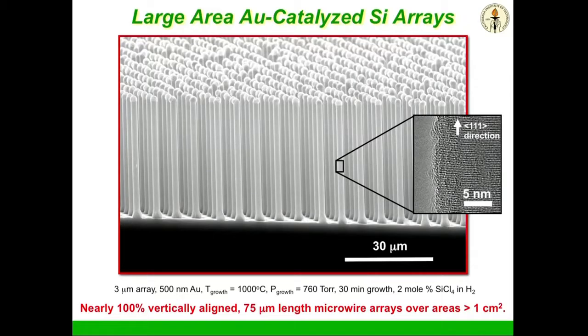We've now scaled this up in barrel reactors on 6-inch wafers. We've grown square meters in our lab just within the last month by this fashion, at atmospheric pressure, with no vacuum conditions, in what literally is like one of the commercial toaster ovens that you pass the substrate through, leave it there for a little bit, and out the other side comes such a system. We then test this with an inert liquid, and we showed that indeed our physics predictions were right.